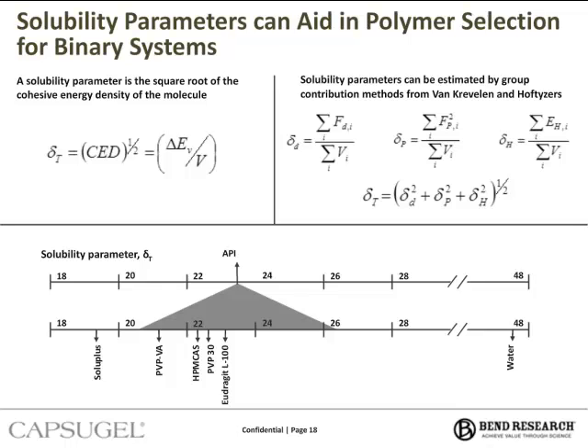And as you can see on the right, this total solubility parameter, denoted delta T, is a function of the individual solubility parameters, the first one being dispersion or van der Waals forces, the second one being intermolecular hydrogen bonding forces, and the third one being intermolecular polar forces. And what we will do is, once we have the solubility parameters for the API and for the polymer, we will rank order polymers for expected solubility at processing conditions. And the closer the solubility parameters, in general, the higher the drug loading that will be possible.